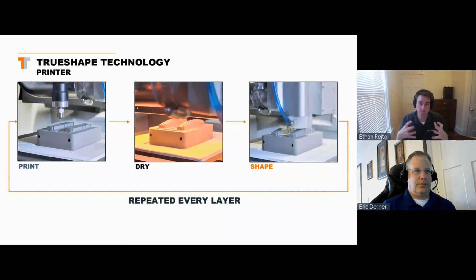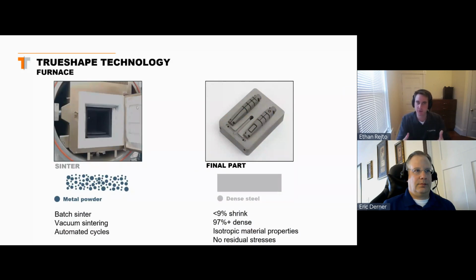It's mostly just metal powder held together with a little bit of binder. We're going to put that into a sintering furnace. I'm not sure how many people on the line here are familiar with press and sinter technologies or metal injection molding, but a very, very similar process where we're going to put it into a furnace. This is a batch sintering furnace. The part's going to get just below the melting temperature of the material.